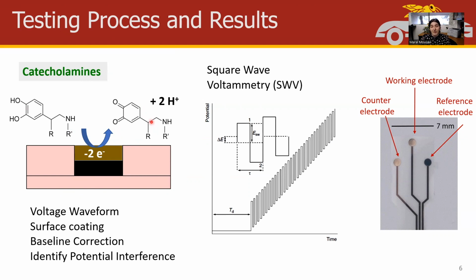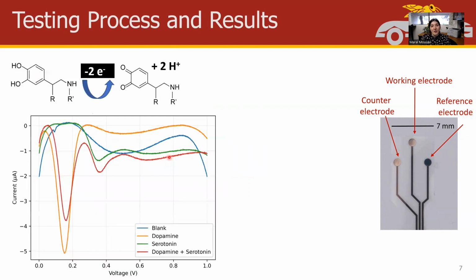Through this project, we've been optimizing the waveform, and the baseline correction, and the surface coating employed in order to enhance selectivity and sensitivity. I'm showing you one plot that we achieved with these electrodes. You can see that the peak for dopamine appears at a different potential versus the peak for serotonin. And that enables us to get selective readout of these catecholamines just through controlling the potential of our electrodes.